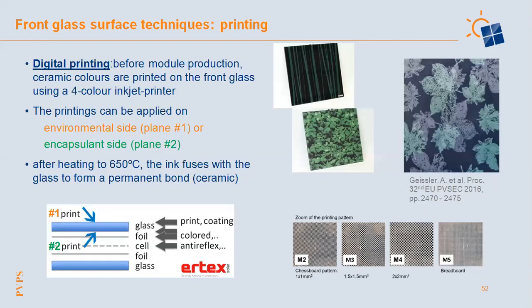The other technique to modify the glass surface is printing, either by digital printing. Before module production, ceramic colors are printed on the front glass using a 4-color inkjet printer. By using that, you can really generate each color you want, and not only uniform colors, but also printing different patterns or photos on the glass is possible. You can print either on the environmental side, so we call it plane 1, that's the outside, or on level 2, plane 2, that's the side next to the encapsulant.